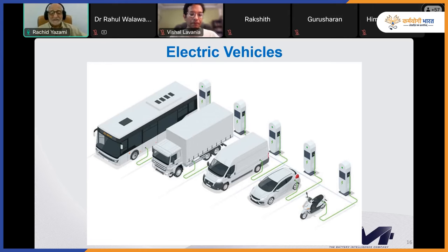So it's not too bad, and this will only increase, because as I said, for this application in electric mobility, we need higher energy density to enable longer driving range. The driving range has been increasing for the last 10 years. Some of the Tesla cars can go up to 600 miles now. Some in China claim 1,000 kilometers. It's possible, but with the current batteries, we have to have a very heavy and very bulky battery pack. So this is not the best solution. That's why we need to increase energy density, which means that for the same amount of energy in kilowatt hours, we have a battery that is lighter. This is very, very important.